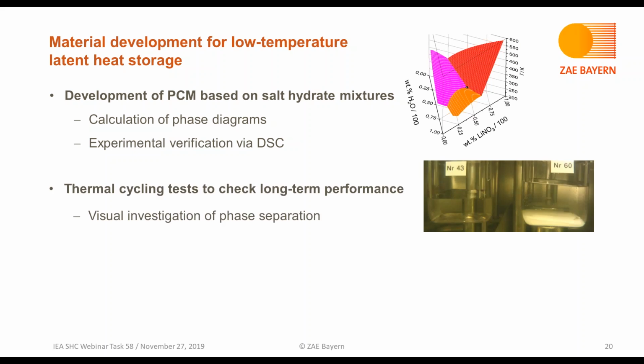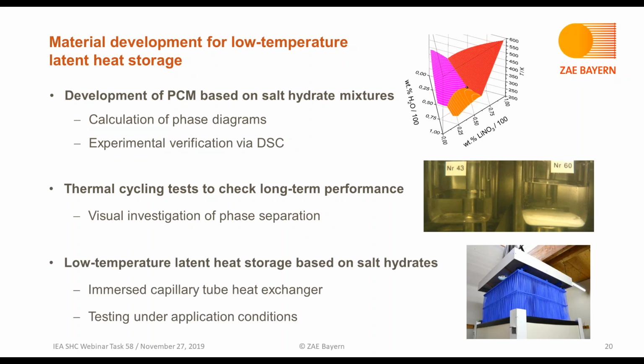The second step would be to perform thermal cycling tests in order to check the long-term performance of these materials. And as you have seen, it is very useful to visually investigate the phase transition, and thereby being able to investigate possible phase separation processes. And in the end, this material development can be transferred to the concept of low temperature latent heat storage using an immersed capillary tube heat exchanger.